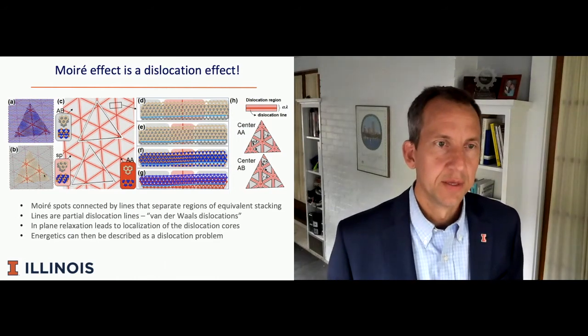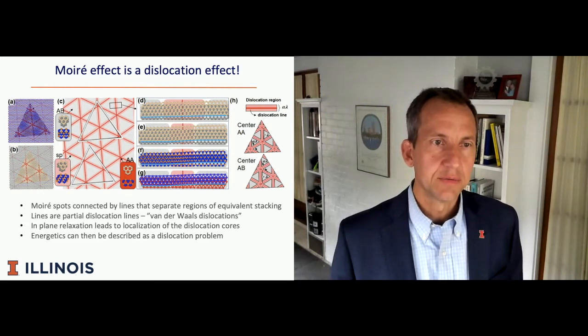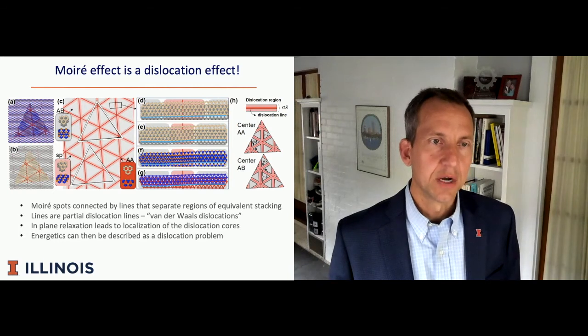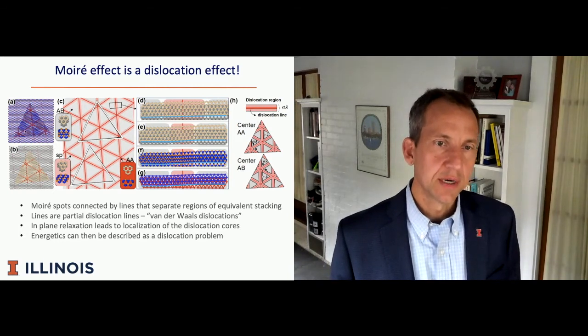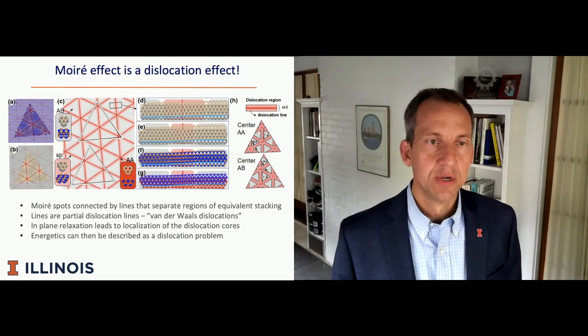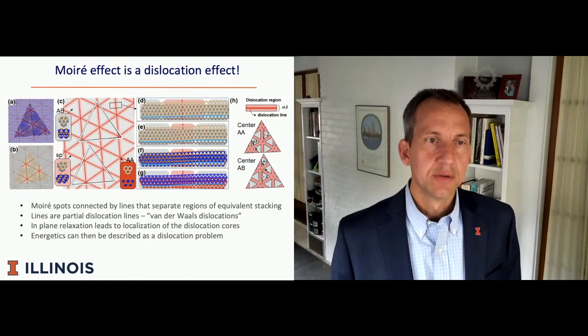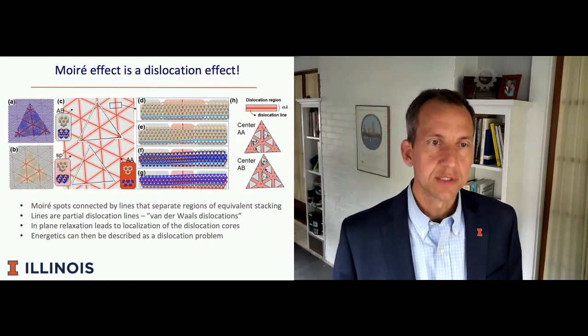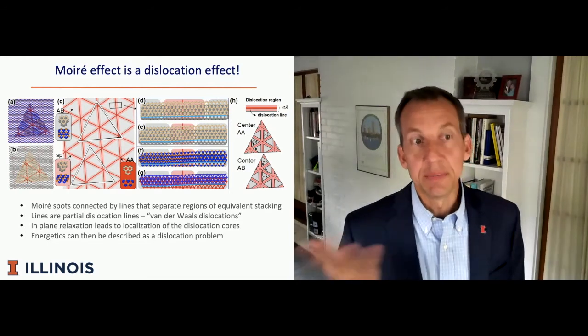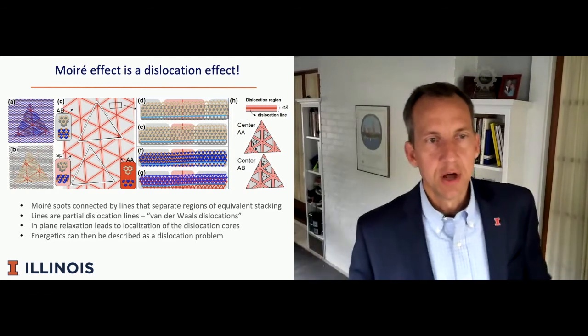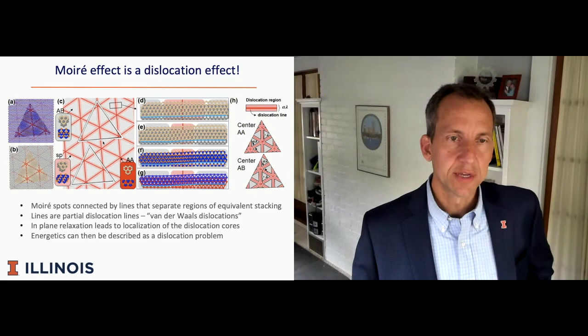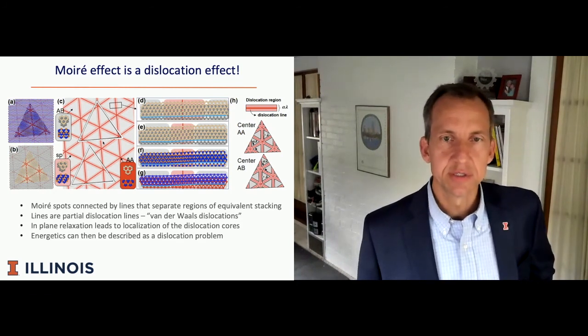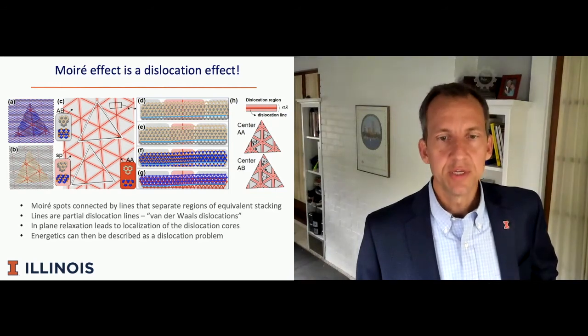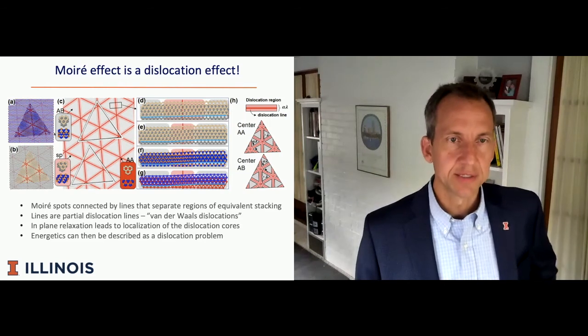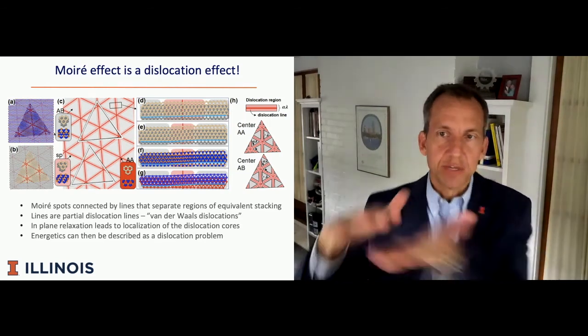Here's what we mean by that. If one looks at the flake and the stacking of the flake on its substrate, the moire patterns contain spots that are connected by lines, if you like, that separate regions of equivalent stacking. So within this top left corner figure, the reddish lines are separating regions of stacking that are equivalent. AB stacking separated from BA stacking, separated from AB stacking, and so on. Along the lines, we have features that are dislocations in the plane. These dislocations are, in fact, partial dislocations. We call them van der Waals dislocations as a sort of nickname, because what's happening is the formation of a dislocation in the van der Waals interface between the layers.